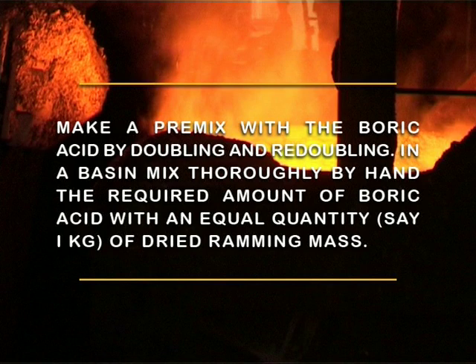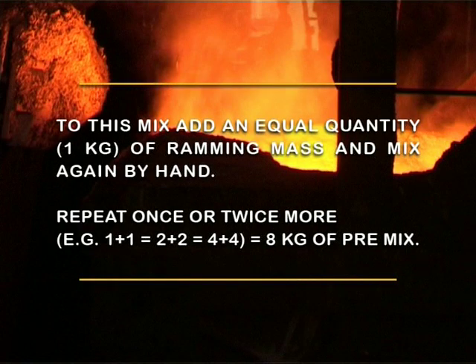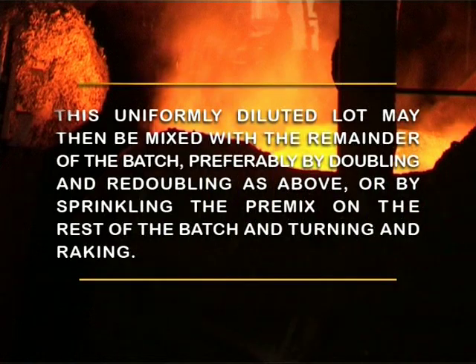Make a premix with the boric acid by doubling and redoubling. In a basin, mix thoroughly by hand the required amount of boric acid with an equal quantity, say 1 kg, of dried ramming mass. To this mix, add an equal quantity, say 1 kg, of ramming mass and mix again by hand. Repeat once or twice more. This uniformly diluted lot may then be mixed with the remainder of the batch, preferably by doubling and redoubling as above, or by sprinkling the premix on the rest of the batch and turning and raking.